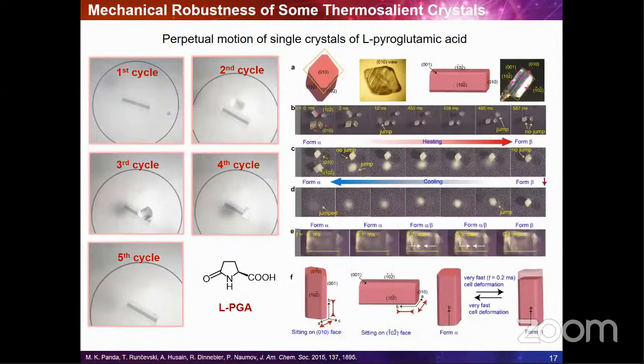An alternative strategy would be to use some of the so-called class 3 thermosalient solids. One of them is shown here, it's just pyroglutamic acid. And in this case, this crystal includes extended hydrogen bond networks in its structure. And so this subset of thermosalient materials is known to be much less prone to disintegration because there is a more effective dissipation of the elastic energy through these hydrogen bonded interactions.